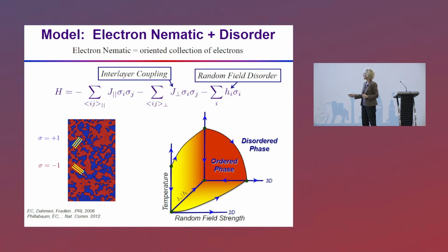We allow that interaction to be in the plane, of course. It's a layered system, so there should be interactions within the plane. Because of the layering, the interactions are weaker between planes, so that's why I pulled off this interlayer coupling. That allows us to change that parameter all the way from a 2D system, where maybe the interlayer coupling isn't important and maybe we should just think about 2D correlations here, all the way to a fully three-dimensional system. Now, how should we model disorder in this system?